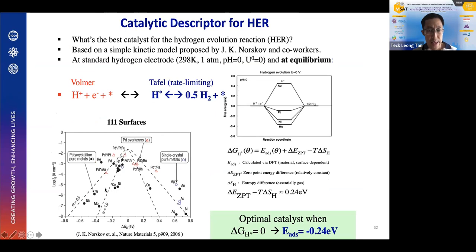If you look at the diagram on the left, if you're familiar with Jens Nørskov's work, who is a very famous computational catalyst researcher, you can use this kind of volcano curve to design promising materials. What the volcano curve is telling you is that hydrogen is adsorbed on the catalyst surface, and depending on the adsorption energy, given by the x-axis, if the adsorption free energy delta G_H is close to 0, this would be a good catalyst. So it illustrates that for this particular reaction, the hydrogen evolution reaction, platinum is a very good catalyst because it is very close to the peak of the volcano curve.